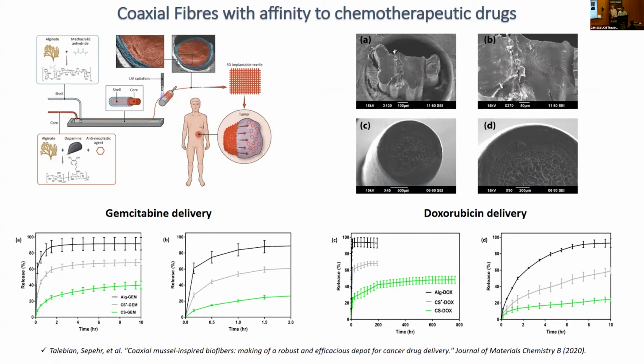So we would have this dopamine functionalized alginate in the core of these fibers, and then to further slow down the release of these drugs, we would add a shell that is mainly made up of alginate methacrylate, which is basically UV cross-linkable alginate. And then we would get these coaxial fibers, which later on can be used individually or can be weaved, or different textile manufacturing can be used to make these implants, which can ultimately be implanted next to the tumor.